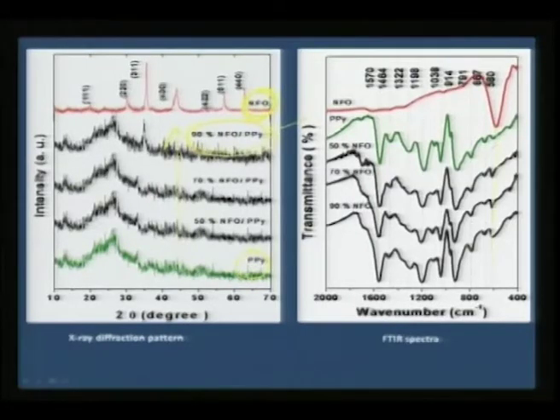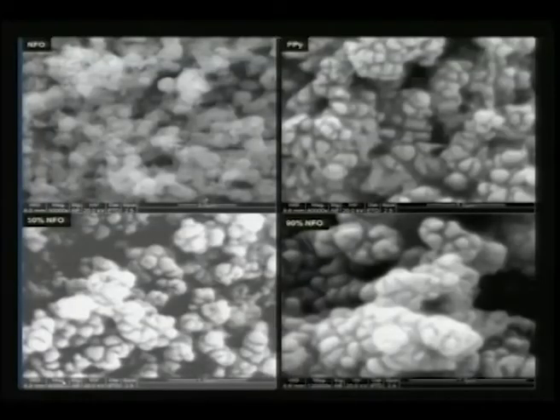This is the typical stretching pattern for nickel ferrite, and you would see only with 90% of nickel ferrite you see this intensity of the peak growing. So, this clearly proves that you can intimately coat the nickel ferrite particles with polymer, and you can also see that there is typically no change in the morphology for polypyrrole and even 90% nickel ferrite, which means the morphology of the polypyrrole is retained even for a 90% composition, whereas nickel ferrite has a different SEM image.